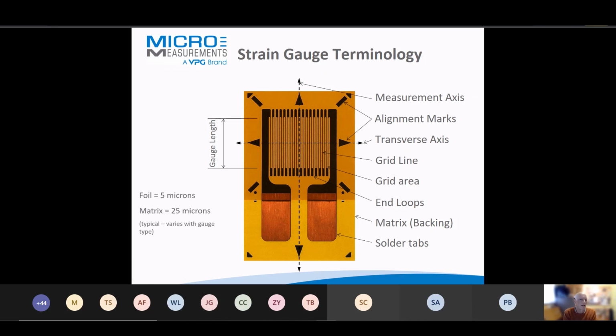When we say very thin, let's define the two things it's made of. Well, the foil, we talk about 5 microns, although we are rolling foil down to 2.5 microns on occasion. And the matrix, typically 25 microns. It can be thinner with some strain gauges, thicker on others. But we are talking about a device that is something like half the thickness of a human hair overall. A typical human hair is around 50 microns. The foil is 1/10 of that, and the matrix is half of that. So it's a very, very thin sensor. One thing to note, by the way, this is a traditional strain gauge. Notice that they have this serpentine pattern with the end loops, and we'll contrast that to what we call the advanced sensor in a little while.